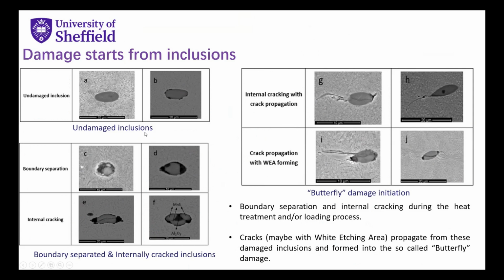But because of heat treatment and loading on the bearing, sometimes we get boundary separation between the steel matrix and the inclusion, and sometimes the inclusion itself may have internal cracks, as shown in pictures E and F—these are internal cracked inclusions. So the stress concentration level of these inclusions will be higher because they're already damaged by this boundary separation or internal cracking.